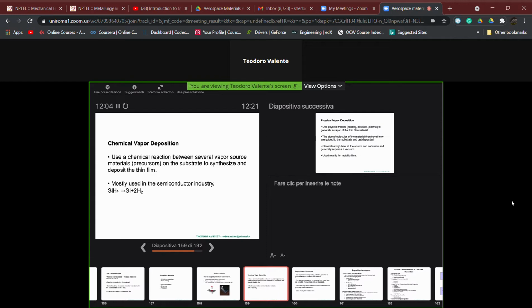So we start from a vapor phase, a gas phase as reactant, material precursors. Then the chemical reaction happens on the substrate. One of the products is a solid. This solid is the coating which is deposited onto the surface. Instead, when it exists, the residual gas phase must be evacuated.